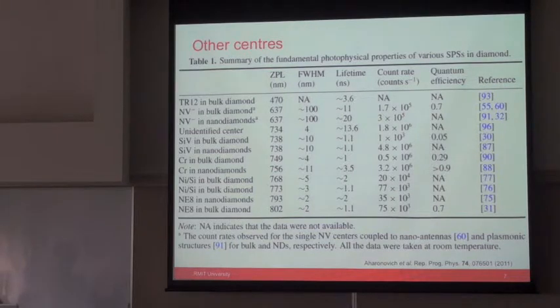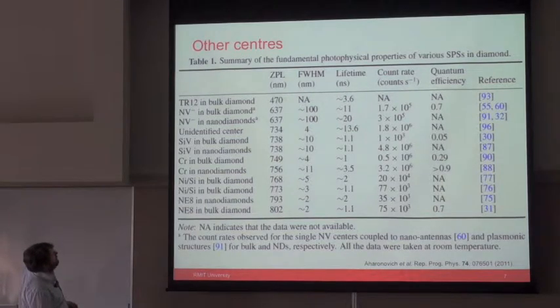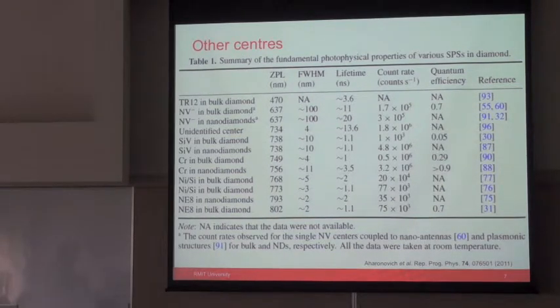Nonetheless, if you're interested in single photon generation, there are far more centers that are of interest, and in fact most of these have more desirable properties than the NV center in terms of much narrower line width, and if you could create these centers on demand, you might have some hope of actually building a single photon source in whatever range you want. The downside, again, is that there's only really 2, maybe 2.5 centers that can be made reproducibly. The NV center is very easy to make. The silicon vacancy center is relatively easy to make. And these nickel silicon complexes, I'd say that's half a center. They have been remade in other groups, but it's not well known. It's early days yet, though.